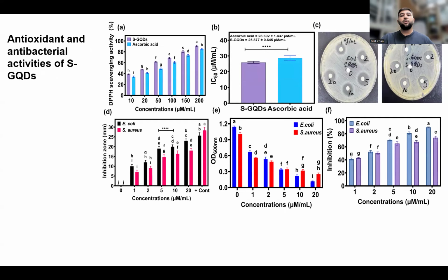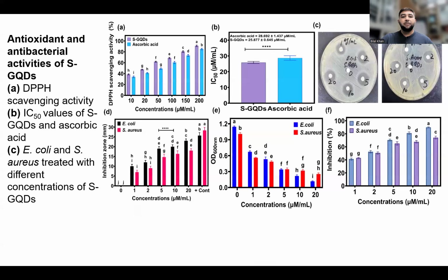Then we explored their antioxidant and antibacterial activities. We did a DPPH scavenging assay to find their antioxidant quality. We used 10 micromolar, 20, 50, 100, 150, and 200. At 200 micromolar, the efficiency of the S-doped graphene quantum dots was more than 90%. It was also surpassing the control, ascorbic acid. So it was very good antioxidant activity.